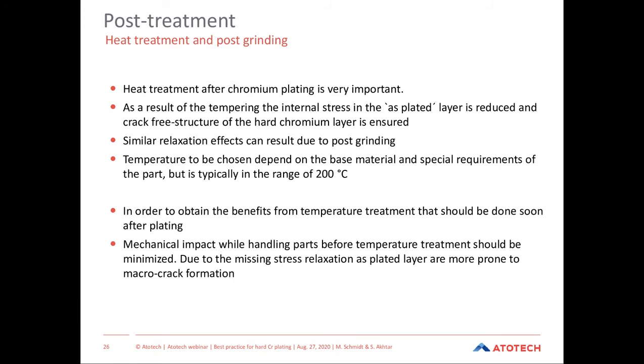Another important area in the post-treatment is the heat treatment or annealing plus the post-grinding. As already mentioned, the chrome plating has very high tensile stress. And with the annealing, the stress release of the chrome layer actually begins. In case of very high tensile strength materials, like for aerospace applications with tensile strengths of more than 1,000 Newton per square millimeter, it's recommended to do a heat treatment in order to remove the hydrogen, which might have migrated into the substrate and can cause tension and stress if it's not removed.